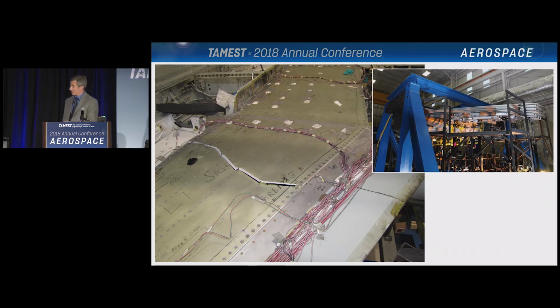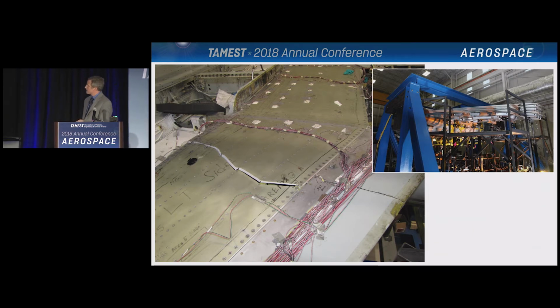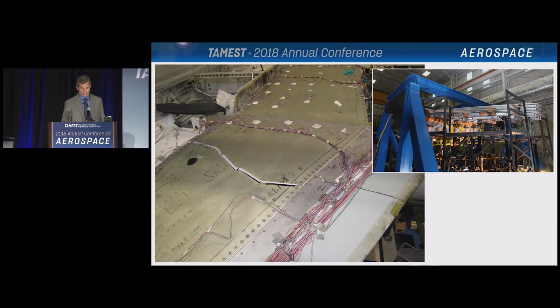After thousands of simulated flying hours, you can see that a crack developed in the lower wing skin and grew to failure. And that skin's over half an inch thick. It broke with a pretty good bang. The T-38's been flying for over 50 years, and tests like these ensure it can keep going safely.